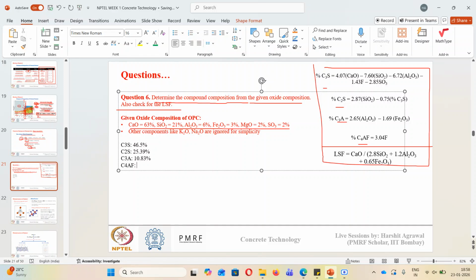So C3S content will be around 46.5%. C2S content will be around 25.39%. C3A content, you will get around 10.83%, and C4AF content will be around 9.12%. And the lime saturation factor will come out to be 0.927. Since it is less than 1, we can say that the cement batch is suitable for use.